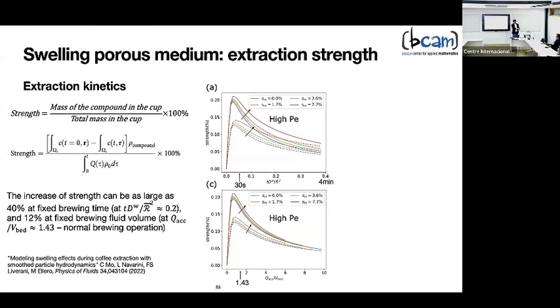This picture has been done at a given brewing time. It's not very fair to show the kinetics of strength in terms of time, because swelling will change the velocity, and therefore essentially mix two effects. So what people usually do in industry is to show the kinetics in terms of volume in the cup. Essentially you do your extraction, and when you reach, let's say, 20-30 milliliters, then you stop the extraction. It's not a measurement of time, it's a measurement of mass. And you can see also in this case, although less than the 30-40% observed here, you have a 10 or 15% increase in the strength. So therefore, swelling, by reducing the flow rate and changing the permeability, will have an effect on the strength.